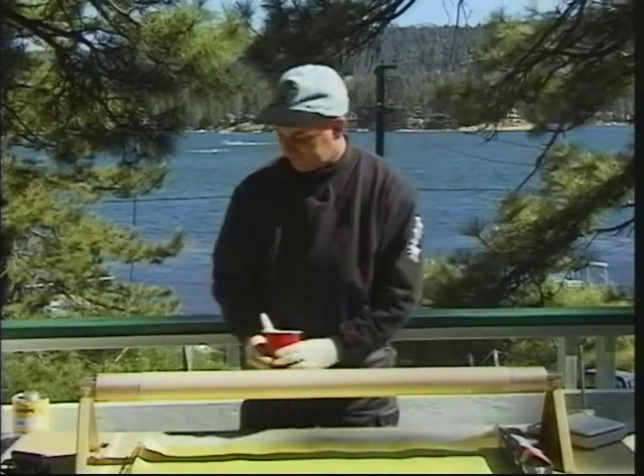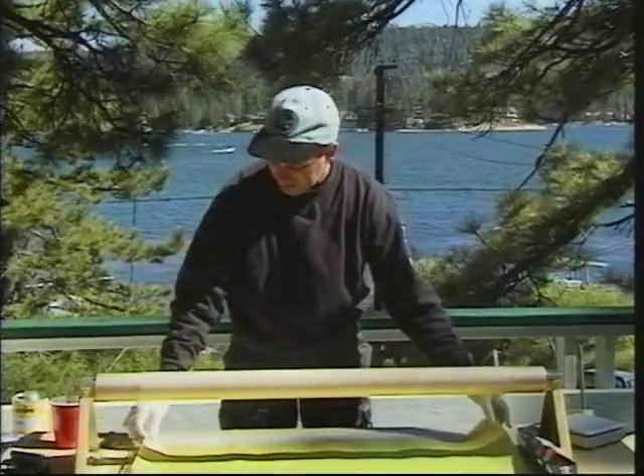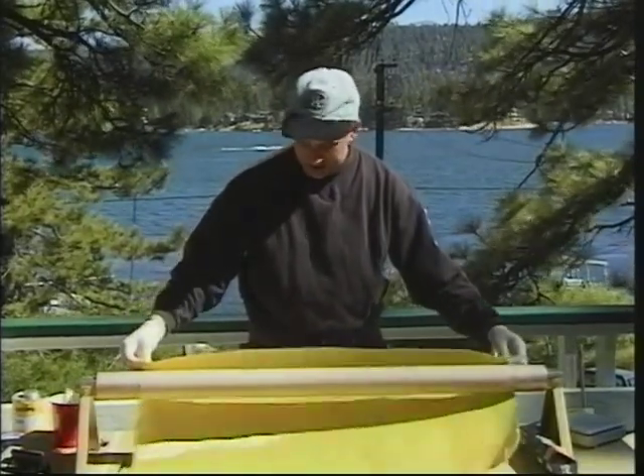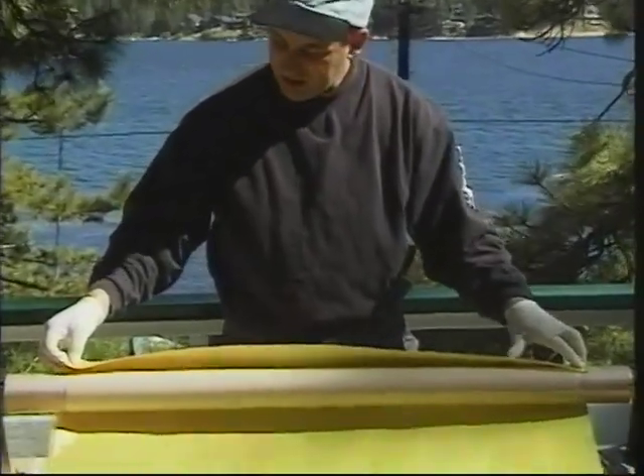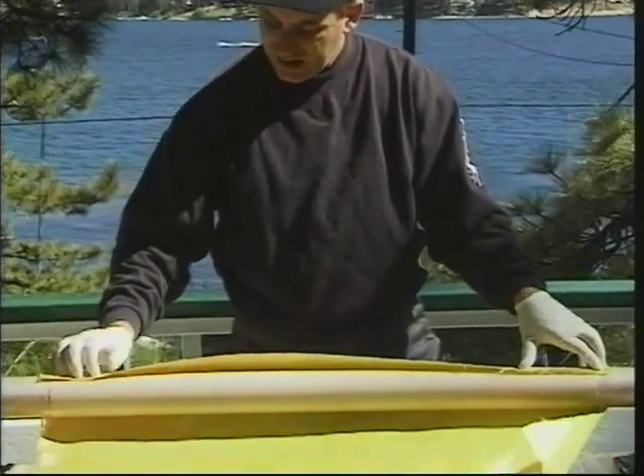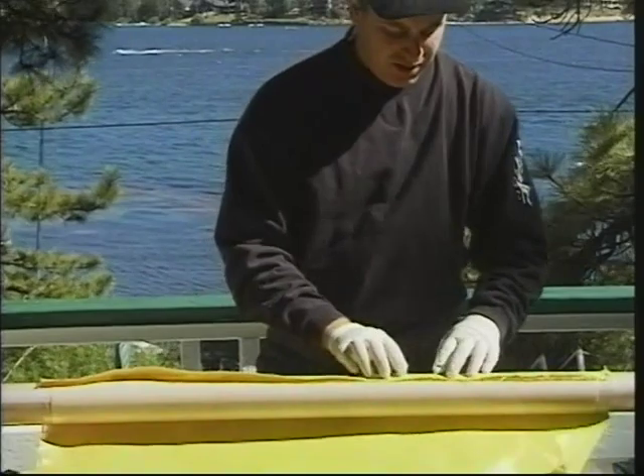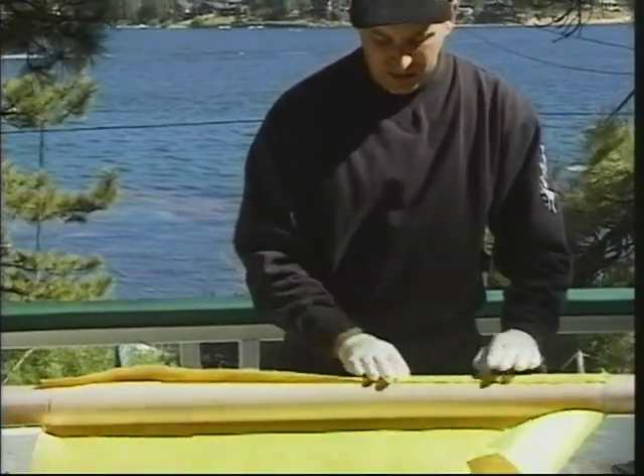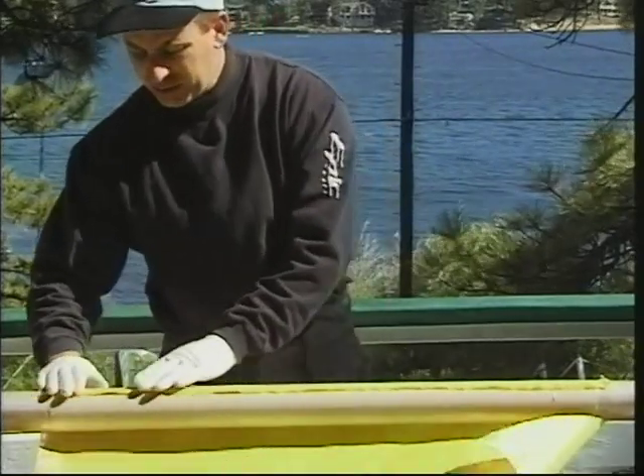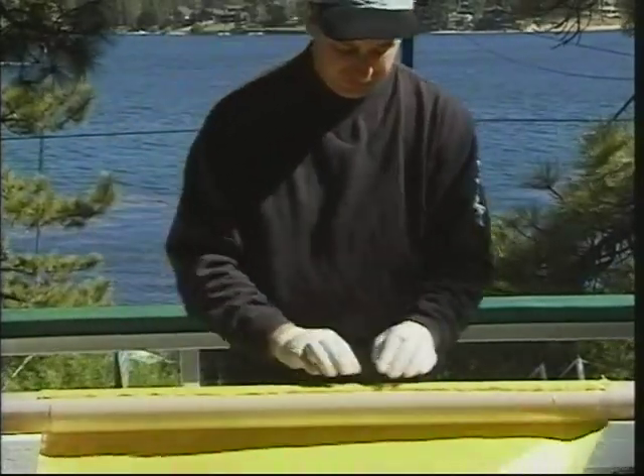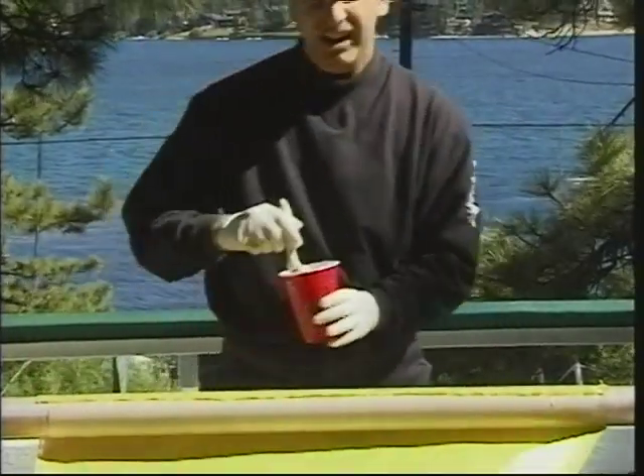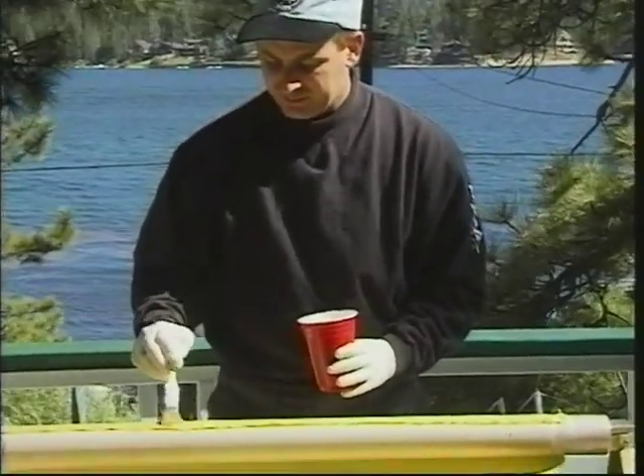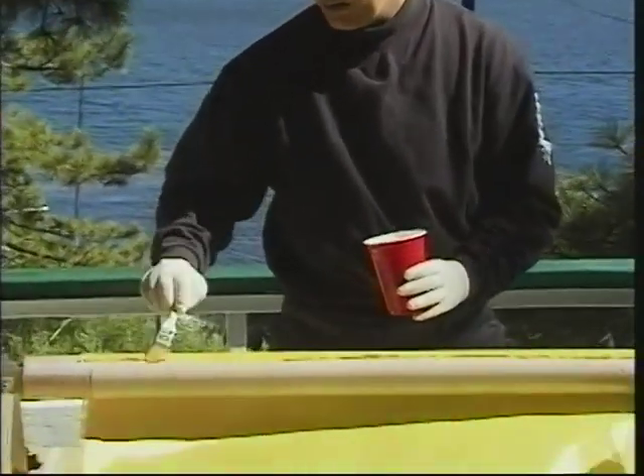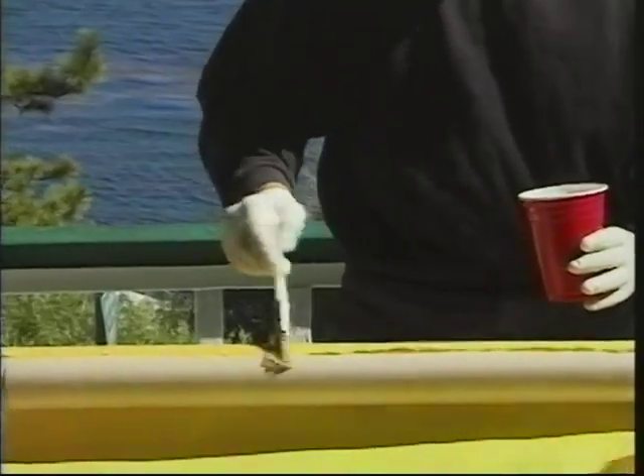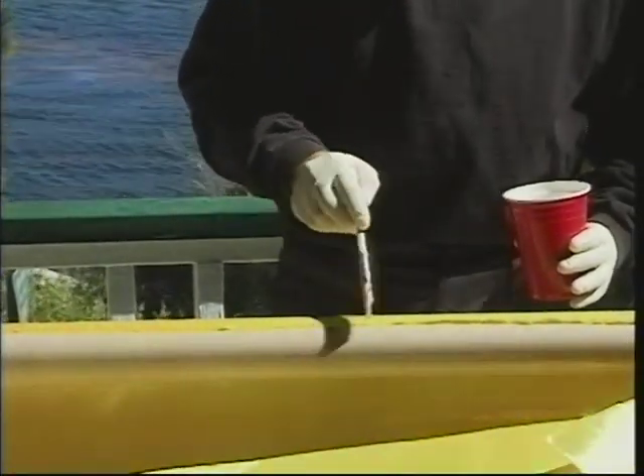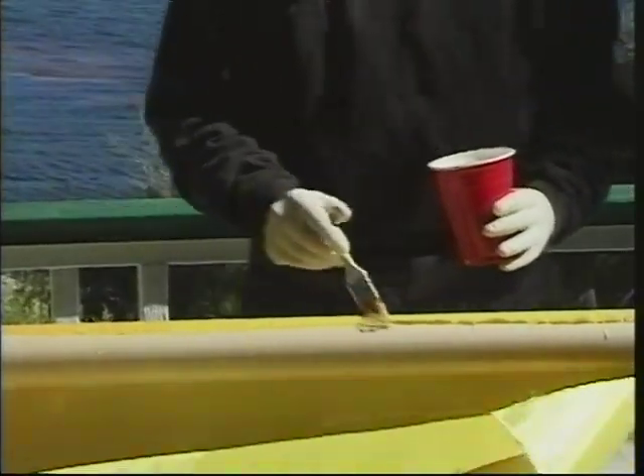So now my tube's covered with resin, and again, here we go winding. This is an 8-ounce Kevlar product, and it's quite moldable and easy to work with. All you've got to do is get all the resin in there. So again, get your rolling technique down all along the edge as you start it, and get that edge to stick down to the tube really well.